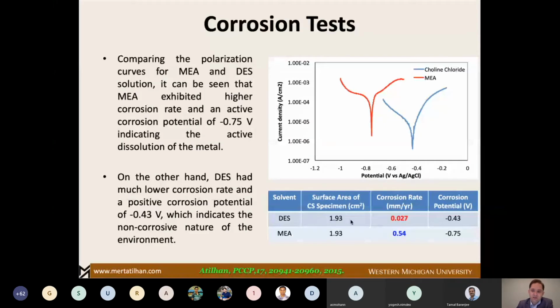But what struck us the most towards the end of this paper was that we wanted to see the corrosion effect, because MEA or amine-based systems are not considered to be used without a corrosion inhibitor in the system. You must have a corrosion inhibitor because these are corrosive materials. That's one of the main issues with the amine system. It has its own side effects on the processing equipment as well. So we had a very simple corrosion cell from one of my colleagues. So I accessed that equipment.